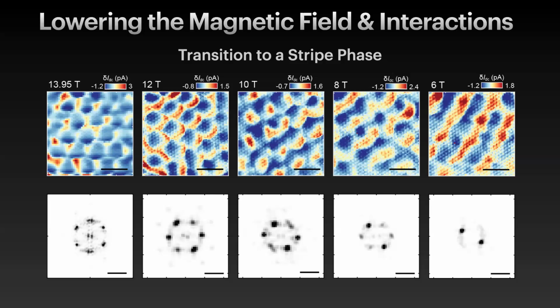So you might ask what's going on here? Why you get, this is in the 0th Landau level of bilayer graphene, why are you getting stripes? We thought stripes were observed in higher Landau levels. Here in bilayer graphene, n equals 0 and n equals 1 are very close. So you can have Landau level mixing that could become enhanced at low interaction strength and low magnetic fields, which might be the reason why the stripe phase is favored in this problem. So there are some new papers by Allan MacDonald and others trying to understand this thing.